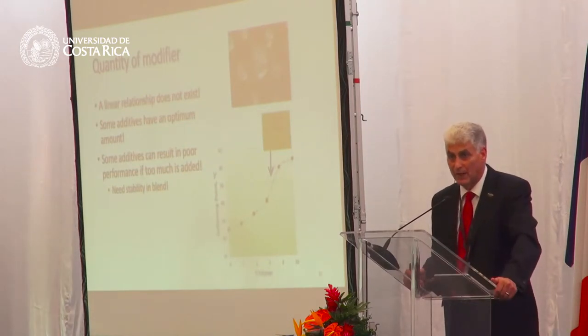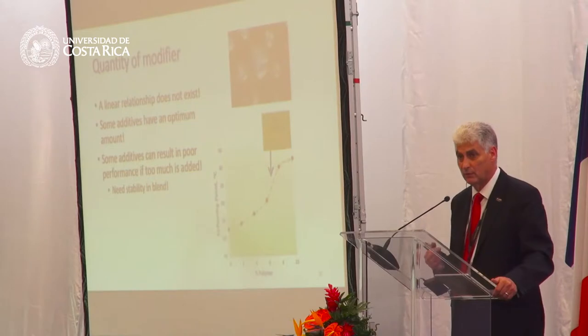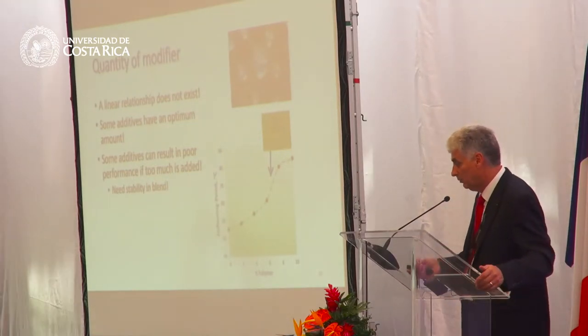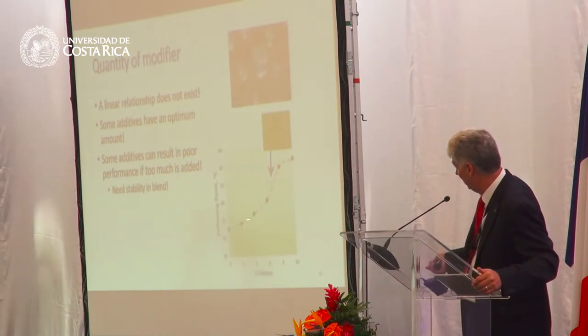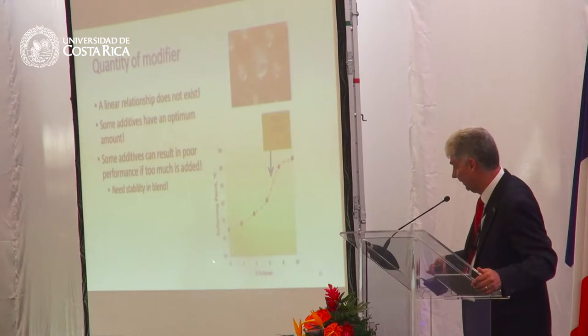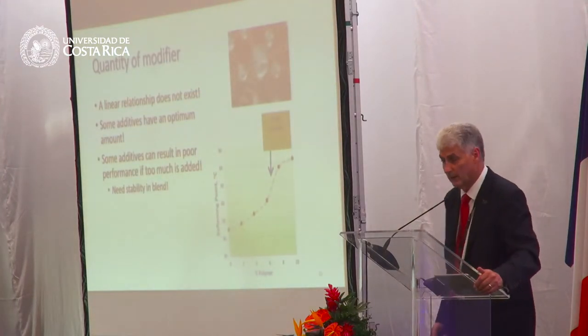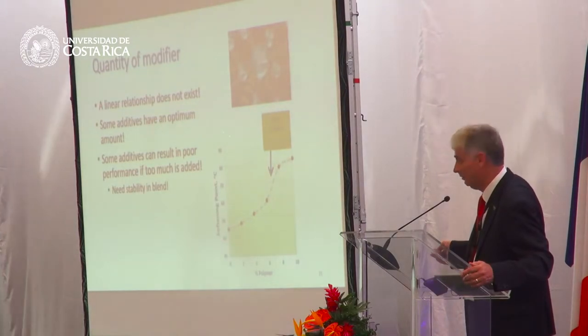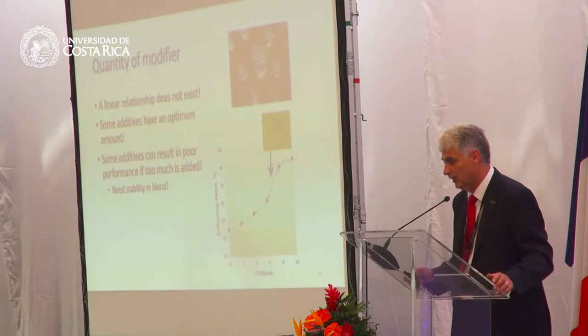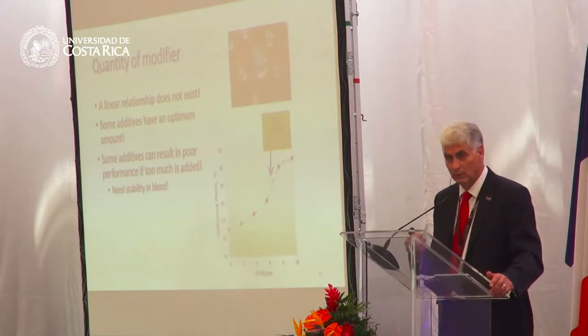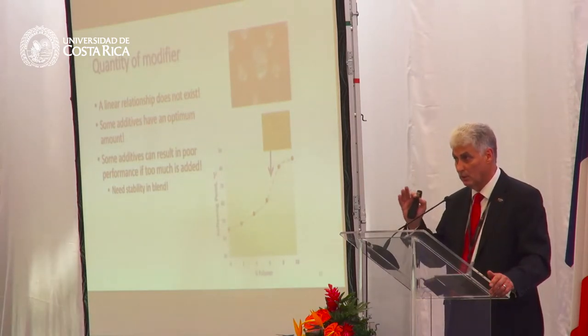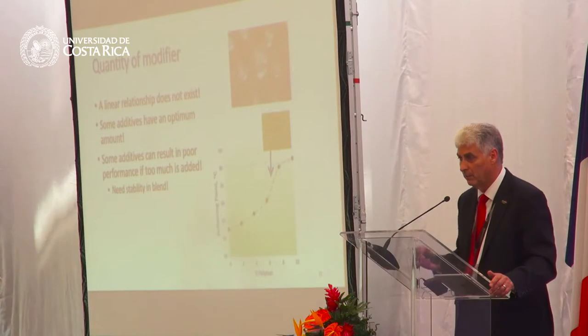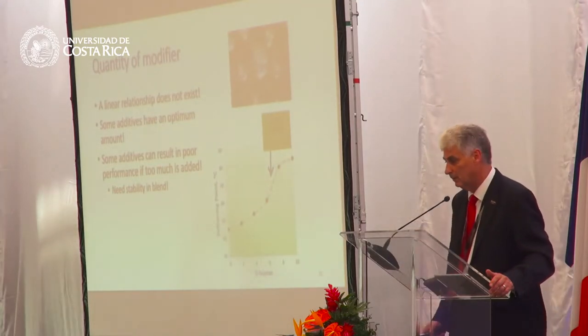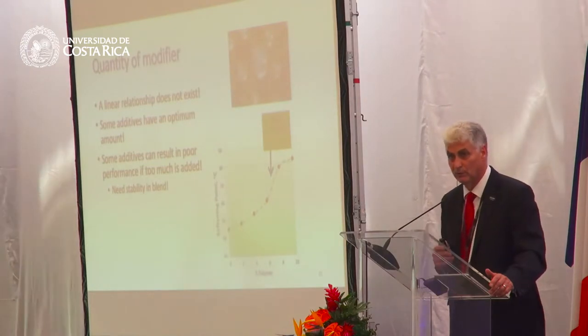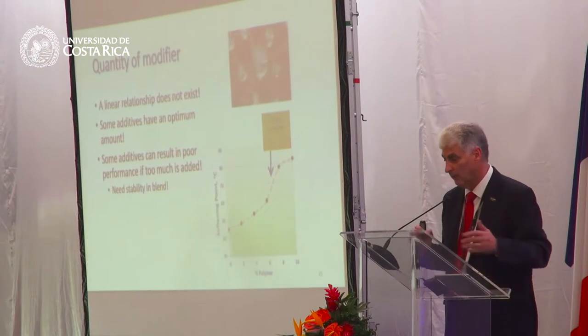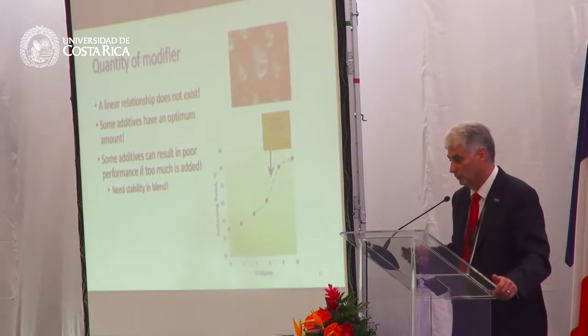In terms of how much modifier we add to a material, we have to remember that these relationships with modifiers aren't linear. And I've just shown this as an example. This is showing the amount of SBS polymer going into a material on the horizontal axis and the change in softening point on the vertical axis. And you can see as you add the material, all of a sudden you get a sudden jump. This is as the network structures and the interactions occur. So with additives, you don't get a linear relationship, and with many additives, there's actually an optimum amount you want to add. It might be 5%, it might be a bit more, but there are optimum amounts of additive that we need to consider. If you add too much of some additives, that can then be bad for the binder. So we have to design our binders very carefully with those sorts of considerations.